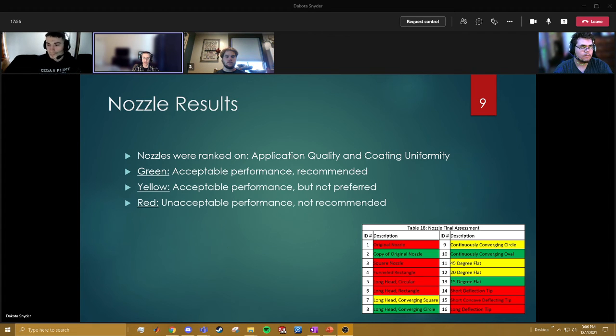Coating uniformity was checked across all samples and compiled. The samples were checked post-baking and post-saltwater testing. Corrosion performance was also assessed after testing and recorded for posterity and legitimacy. The recommended nozzles are the copy of the original nozzle, a long head converging circular exit nozzle, a continuously converging oval exit nozzle, and a 15-degree flat fan nozzle.